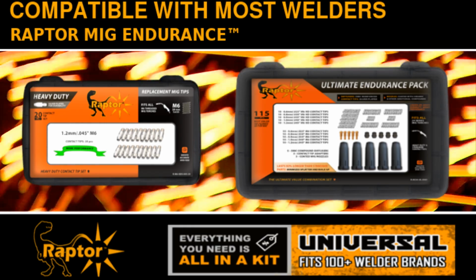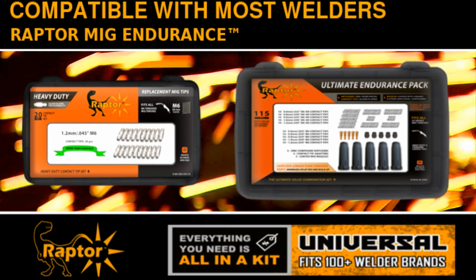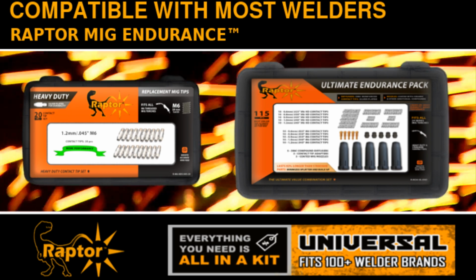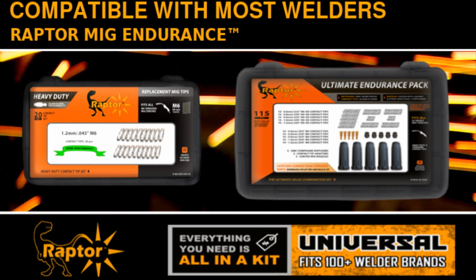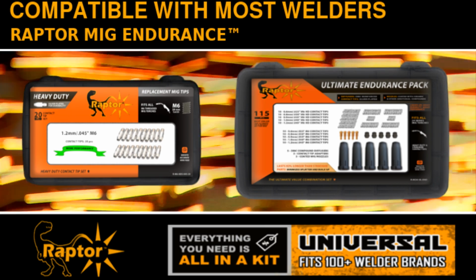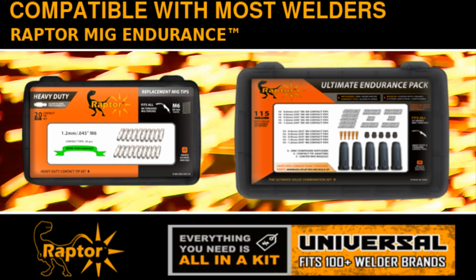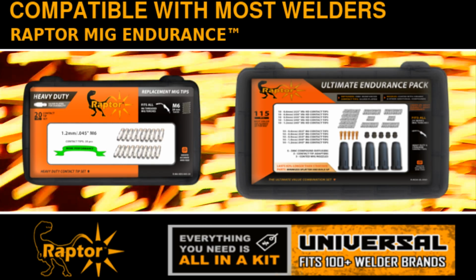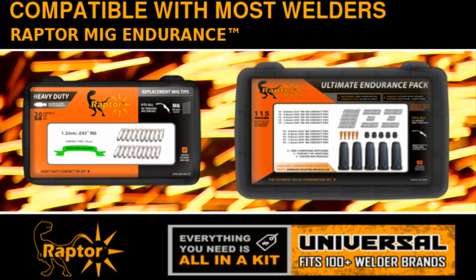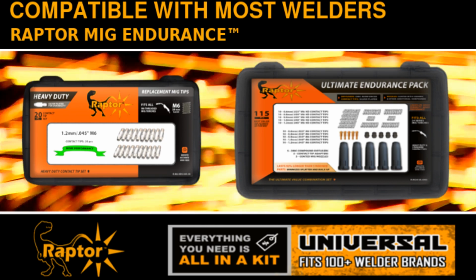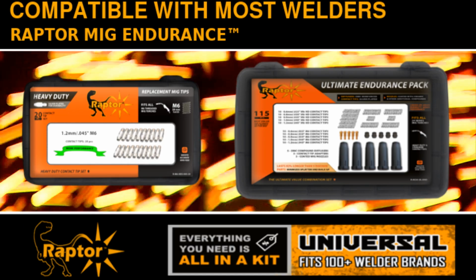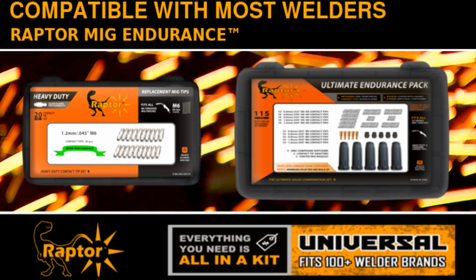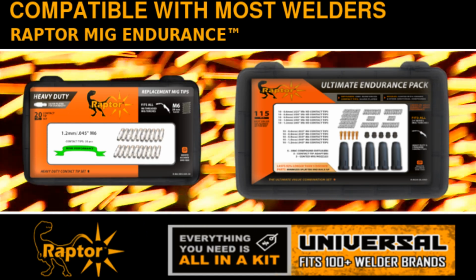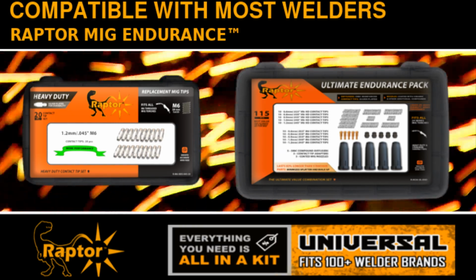The MIG Endurance contact tip offers more than 7 times the life of a standard conventional contact tip, thus again improving the process, while maintaining a clean, focused and splatter-free weld puddle. Depending on thickness of material, this results in 15 to 25% higher welding speed, and longer contact tip life, while extending the life of the torch itself, due to lower generated heating effect.